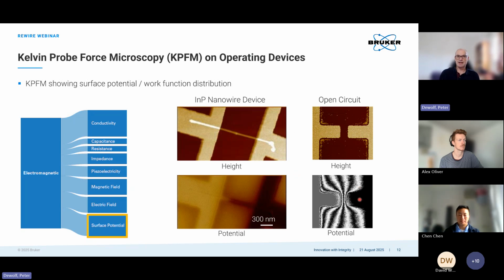So we can nicely see that here. This color scale is chosen on purpose to show the equipotential lines. We can see that there's a strong electric field between the plugs, between the two metal contacts, as expected, with lower field here. We can actually see that field is stronger toward the right side than it is to the left side, and that can be of relevance when we're making devices.